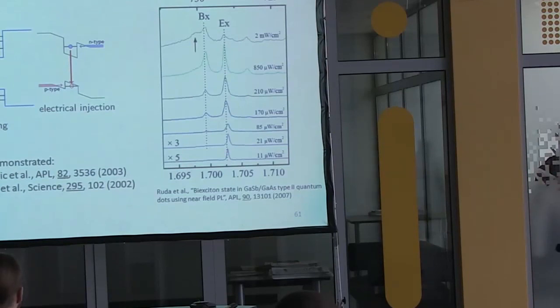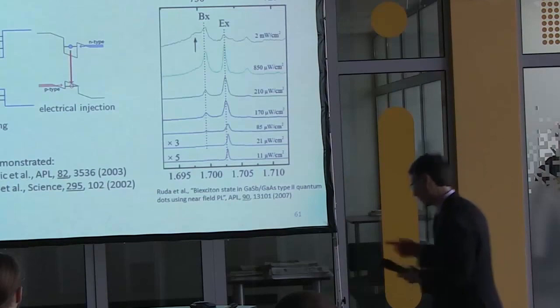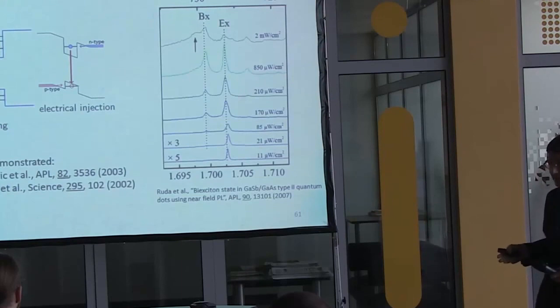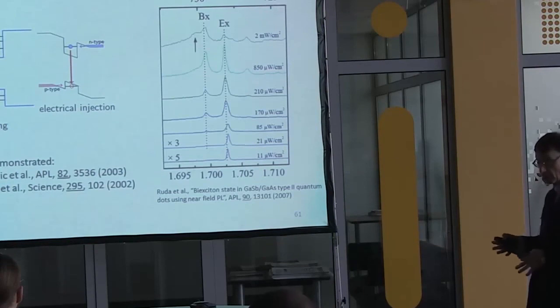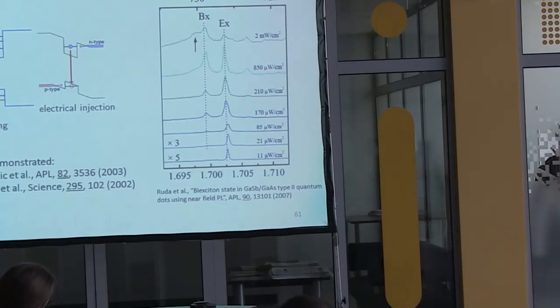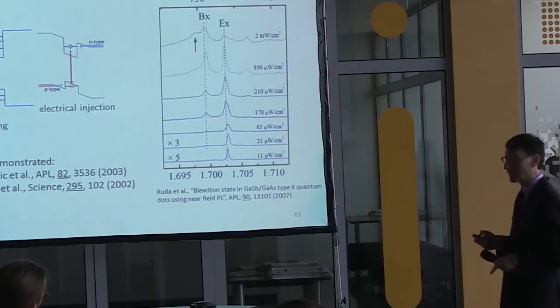Sorry, I'm wrong, this is the pump intensity we're looking at. The luminescence is collected by the CCD, a liquid nitrogen cooled CCD camera. Those are the two axes: the wavelength from the spectrometer, and the intensity as number of counts from the CCD. The reason for this, what I was trying to show, was that at low numbers of photons, the microwatts per centimeter squared tells you the flux of photons that we're exciting with. This was 710 nanometer excitation, slightly higher in energy than these peaks.